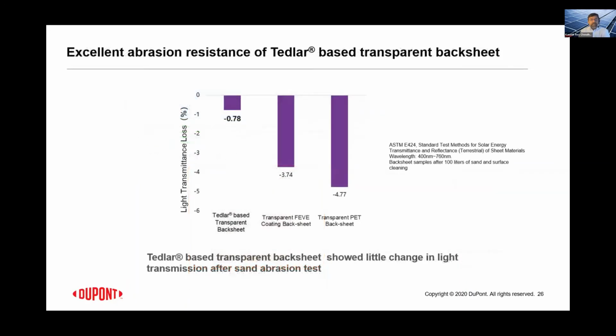Another thing that we check is abrasion resistance of the Tedlar-based transparent backsheet. I'm showing here comparisons of the Tedlar-based transparent backsheet with a couple of other similar products in the market. This is a transparent fluorinated coated backsheet, the second bar, and then the third bar is a transparent PET-based backsheet. What we see here is the transmittance loss after this ASTM test, which is actually a rather harsh test of falling sand on these backsheets. So at the conclusion of this falling sand test for the Tedlar-based transparent backsheet, we see a loss of less than 1% versus 3 to 4 times or even more for the other types of backsheets.